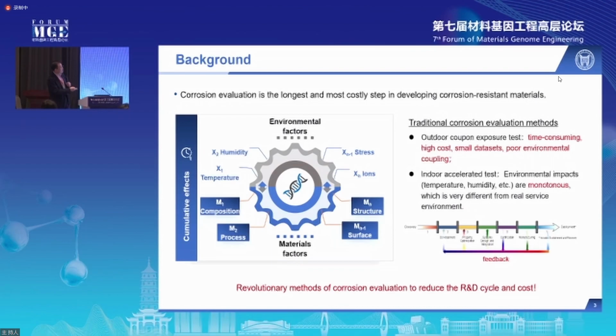The two traditional corrosion evaluation methods include, for example, outdoor exposure, the coupon exposure test, meaning that literally we have a sample, we expose it in a real service environment and take it back after, for example, 1 year, 2 years, and even 10 years. And in the laboratories, we analyze the surface condition and the corrosion depths. But this is, you can imagine, really time consuming and highly costly, and it can only generate very small data sets. And more importantly, it cannot really reflect the impact of the dynamic environment on the corrosion process. And also for indoor accelerated tests like the salt spray test, UV chamber, and humidity test, the environmental impacts generated from these tests are monotonous, which is also very different from the real service environment.